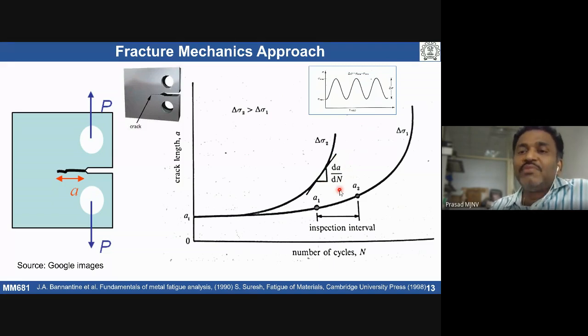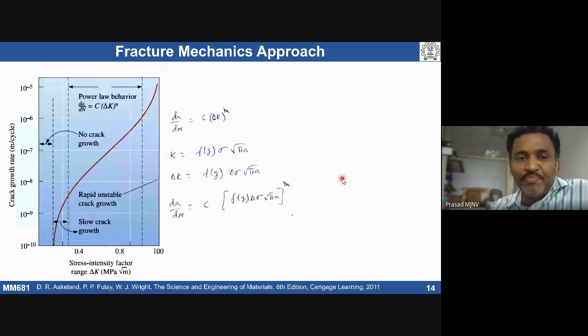So people do establish crack growth rate for different materials. For example, here, by taking a stress intensity factor range, delta K. Basically we know the stress intensity factor K is equal to some geometric function times sigma square root of pi A, where A is the crack length. So this is how stress intensity factor is known from a fracture mechanics approach. And delta K is basically delta sigma square root of pi A.